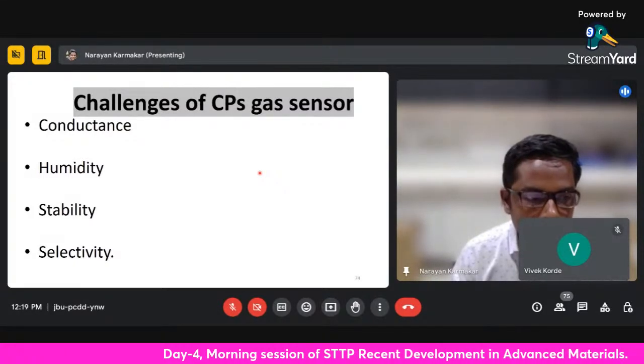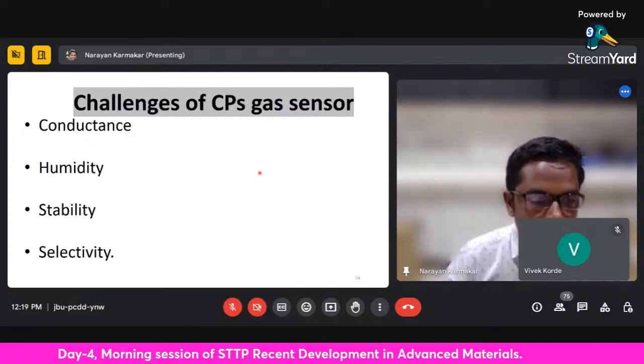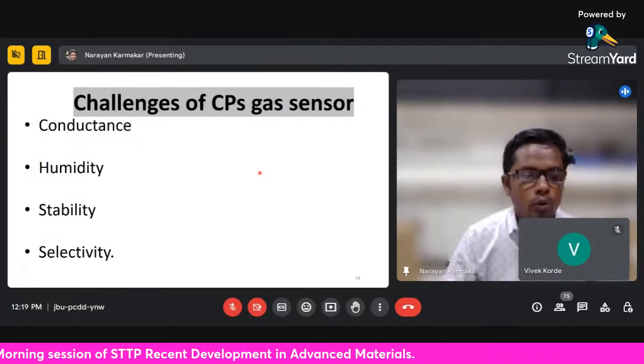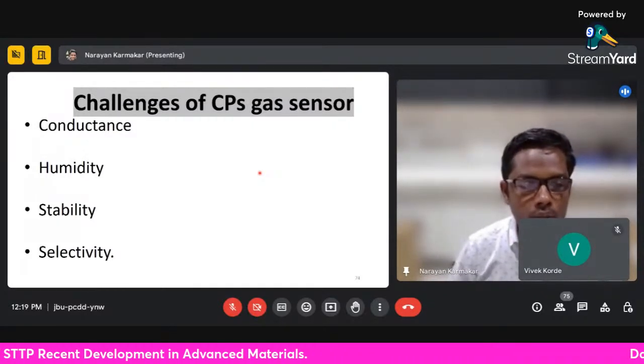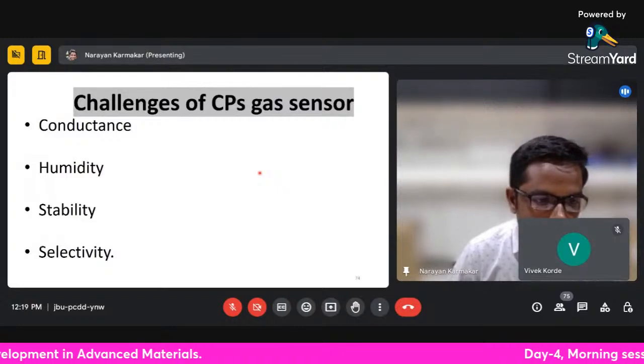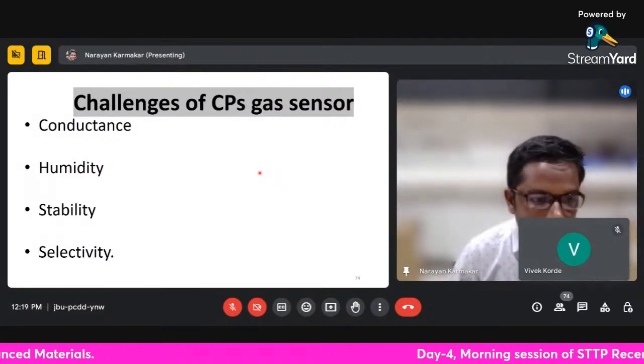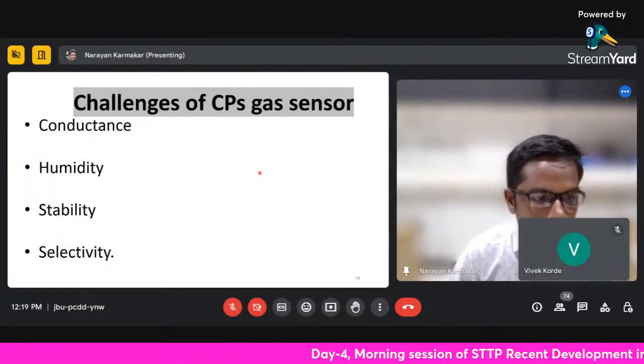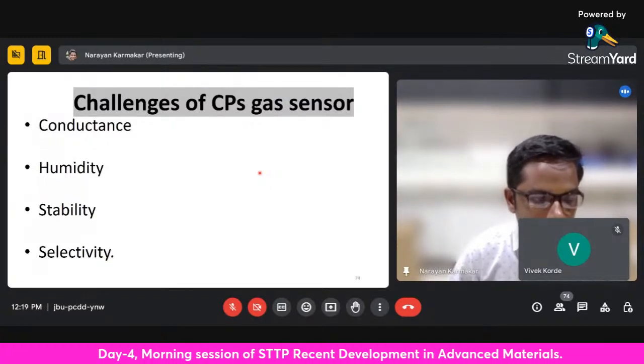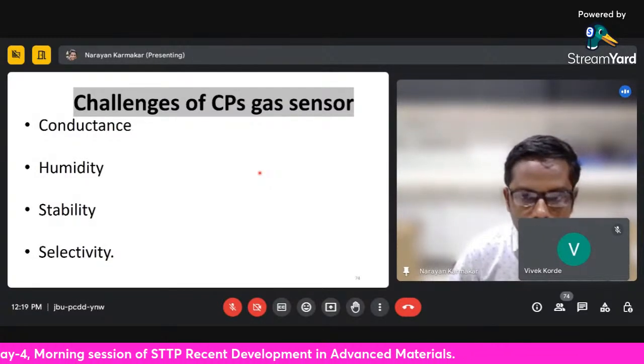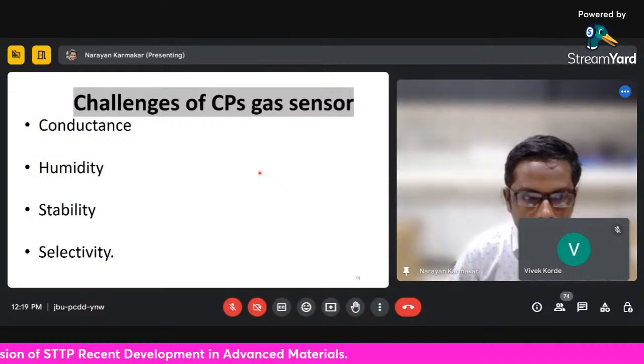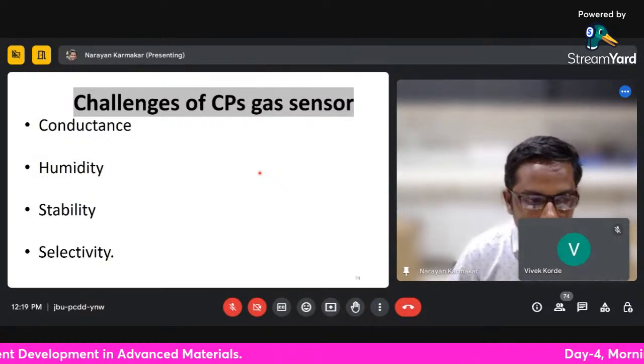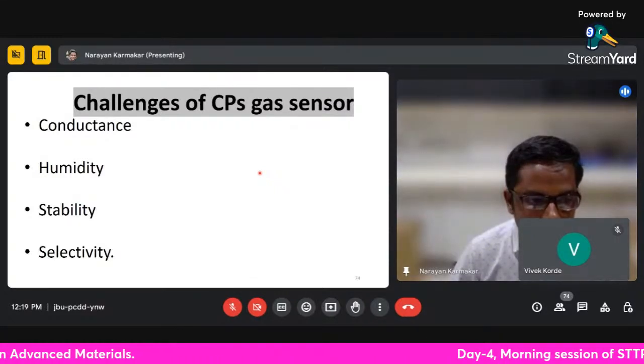And also the main challenges that we face using this conducting polymer gas sensor are stability and selectivity. As in the previous slide, you can see that these sensors are not stable for more than 30, 40, or 45 days. If someone installs or purchases this sensor and it cannot have a stability of more than 40 days, no one will buy the sensor. So one major challenge of this conducting polymer gas sensor is to improve its stability.